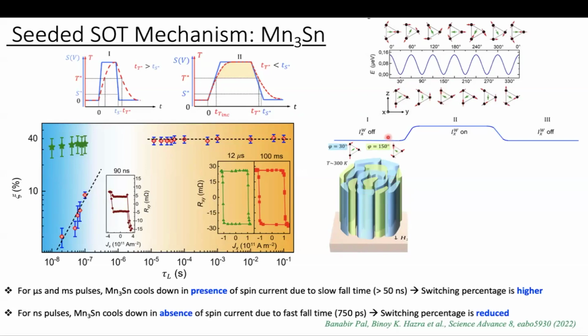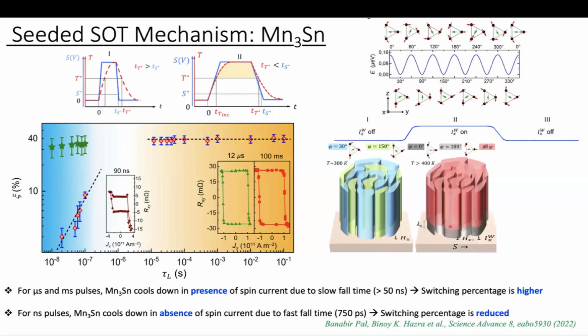When the writing current is off, the domains are equally populated, and then as soon as we switch on the write pulse, the tungsten layer generates some spin current. That spin current propagates and switches the interfacial layer close to the tungsten, a few layers of Mn3Sn, shown here in gray color. Here the domain structure is 0 or 180, whereas initially it was 30 or 150. These are low energy states, and from here it goes to 0 degree or 180. These are high energy states. The complete switching will happen when it crosses 180, which is the barrier, and then reaches 210.